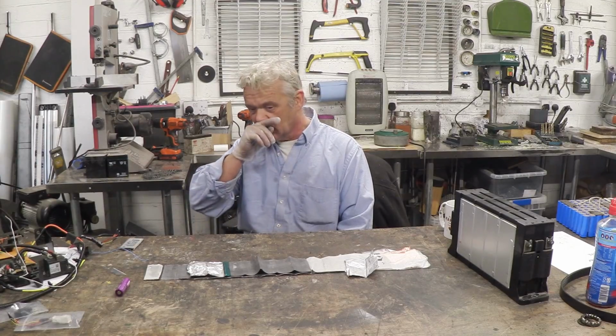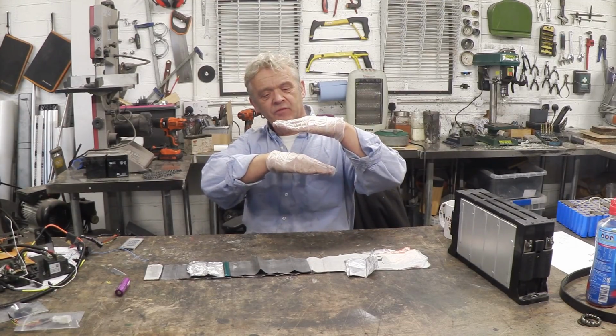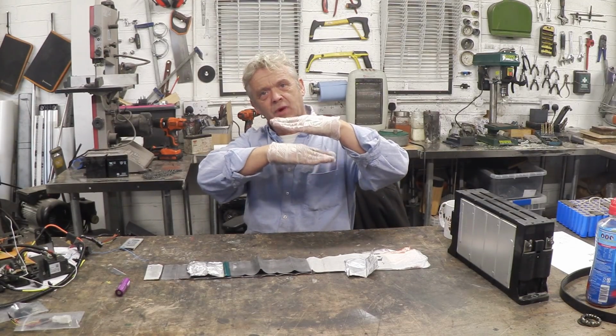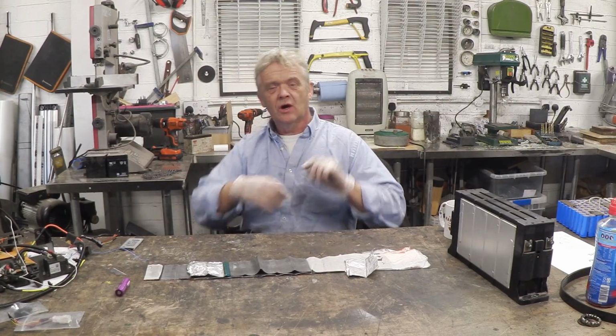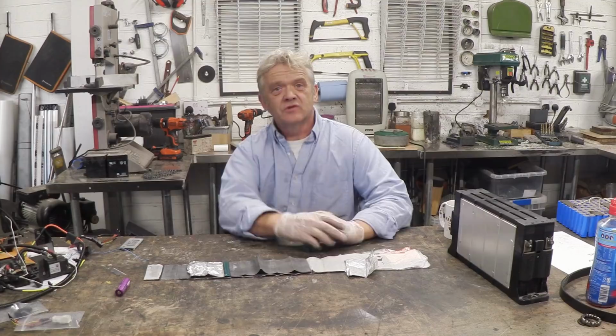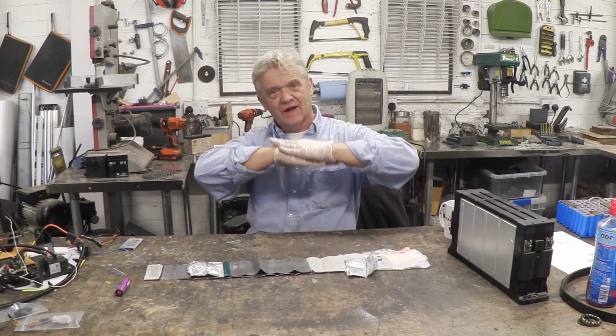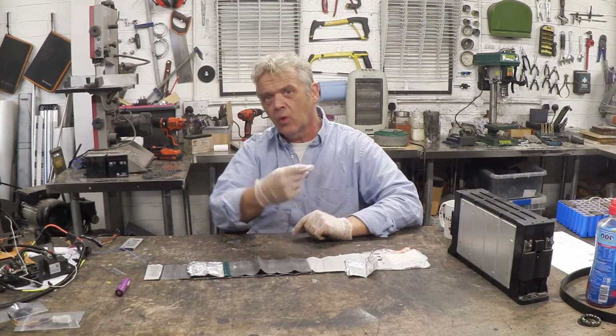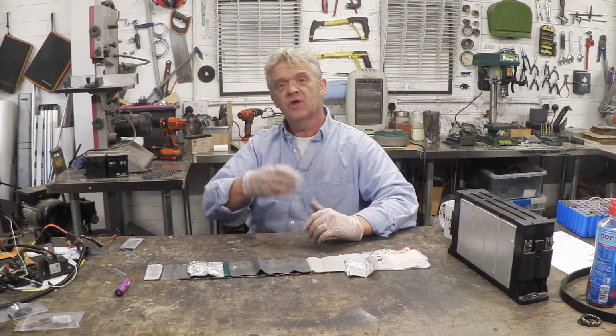Now, lithium is actually kept apart by galleries. It's like a whole load of stacks laid on top of each other, and there are little pillars to keep those stacks apart so the lithium can go in and out. Unfortunately, those little pillars are also made of lithium. So if all of that lithium goes out, then those pillars are gone and the stacks collapse, in which case you can't get any more lithium in and out. Which is why if you discharge a lithium battery down to 0 volts, you ruin it, because you remove all of those pillars, which are lithium, the stacks collapse, and you can't get them back in.